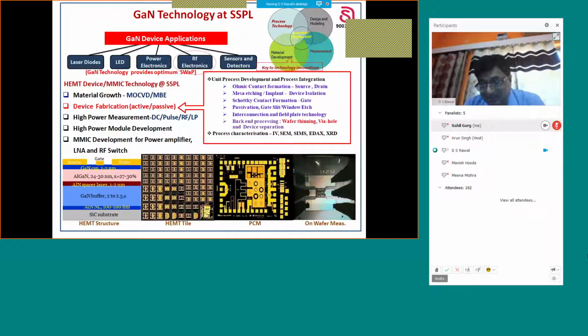But the disadvantage of using silicon carbide substrate, in spite of the fact that it gives best RF performance, is that the processing is very difficult, because it is the second hardest material after diamond. But for RF device fabrication, we need to have reduction in the thickness of the wafer once we fabricate the devices on the front side. So wafer thinning, then via hole fabrication, is a specialized interconnection for low RF interconnects.